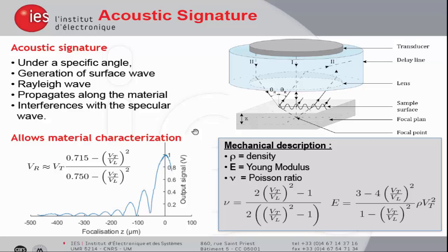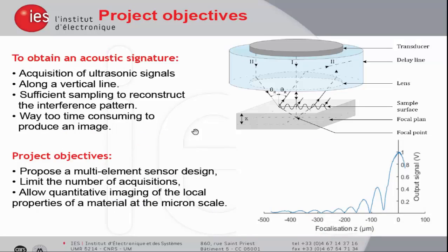This kind of curve is called an acoustic signature, and in fact, it's an interference pattern that is linked to the wavelength of the Rayleigh wave at the surface of the material. And this wavelength, or this Rayleigh velocity, is linked to the longitudinal and transverse velocity, and is also linked through these equations to the Poisson ratio or the Young modulus of the material. It means that by acquiring for a single point a series of signals acquired at the vertical positions of the sample, then you are able to have the Poisson ratio or the Young modulus local property of the material. So the thing is that to perform an acoustic signature, as I've already said, you need a 1D acquisition, in fact, of signals.